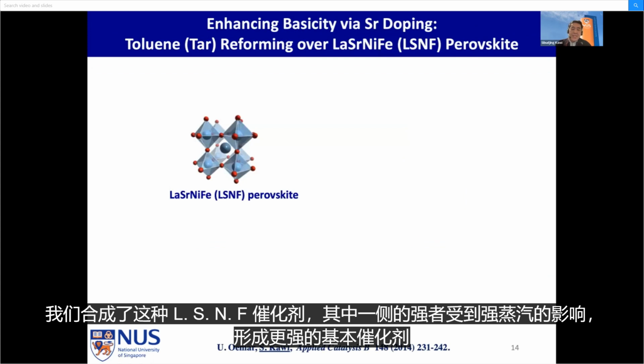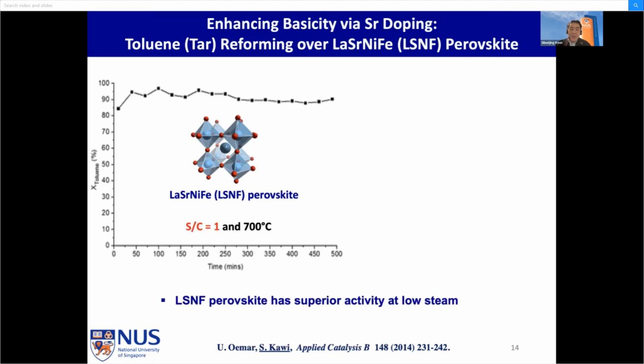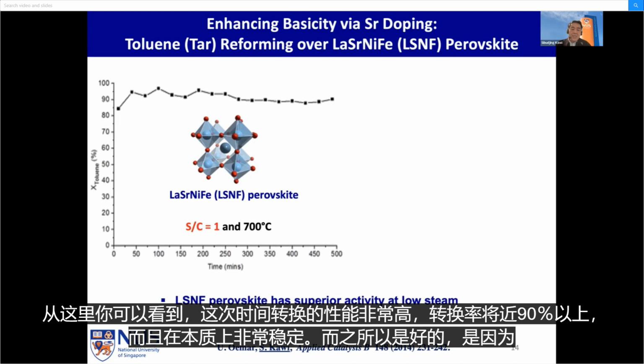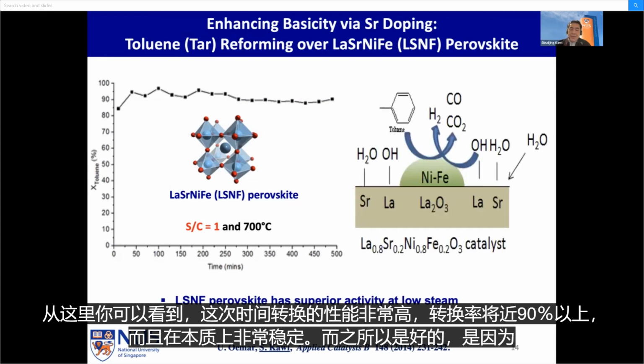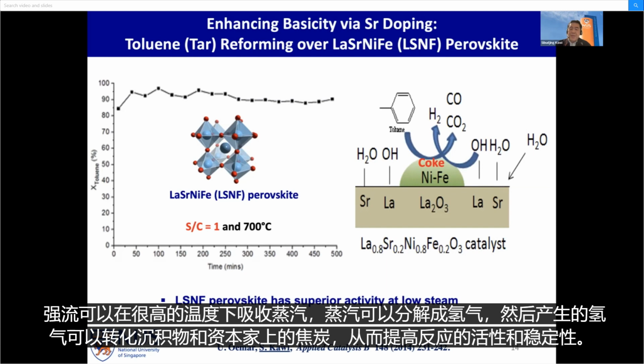We have synthesized this LSNF perovskite catalyst, where on the A site, the lanthanum is substituted by strontium to form a stronger basic catalyst. And you can see from here that the performance for this tar conversion is very high, more than 90% conversion, and it is very stable during the reactions. And the reason why LSNF perovskite is good is because strontium can absorb steam at very high temperatures, and steam can be dissociated into hydrogen, and the hydrogen that is produced can then convert coke deposited on the catalyst, so that it can increase the activity and stability of the reactions.